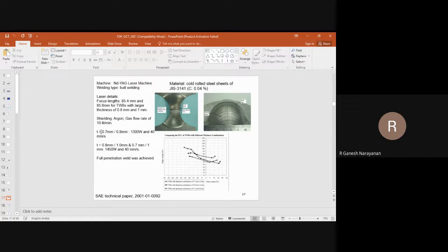Thickness combinations are, you will see, 0.7 to 0.8, 0.8 to 1, and 0.7 to 1. And you want to get a good weld in these combinations, so the power and welding speed also got changed. Okay, welding speed remains the same, 40 mm per second, but power got changed. Only in those conditions will you get a full penetration, and that is why it is changed.